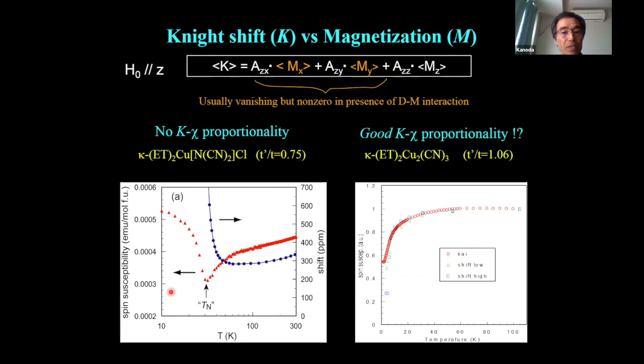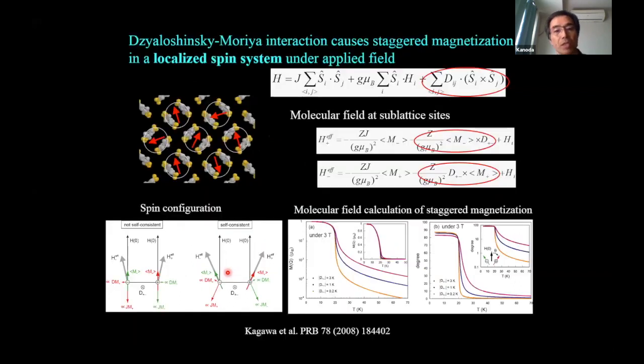However, please take a look at the data of the triangular lattice system case. Temperature and the spin susceptibility are here. The red symbol shows the spin susceptibility gradually decreasing, as I showed in the previous viewgraph, and then Néel order occurs and the spin canting appears here. And the Knight shift is indicated by the blue symbols. The two quantities are not scaled, showing completely different behaviors. But this is very reasonable because there is a Dzyaloshinskii-Moriya interaction in this system.